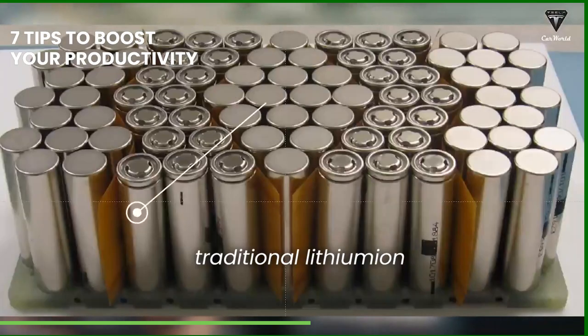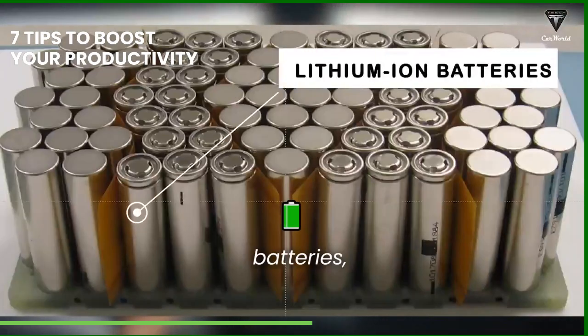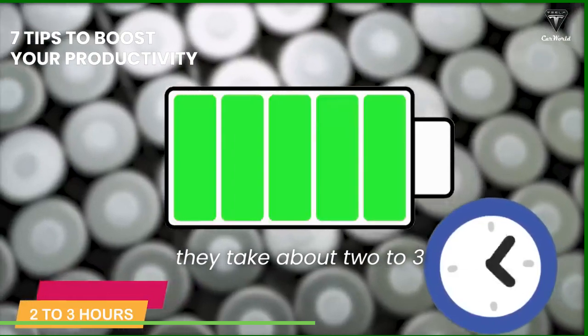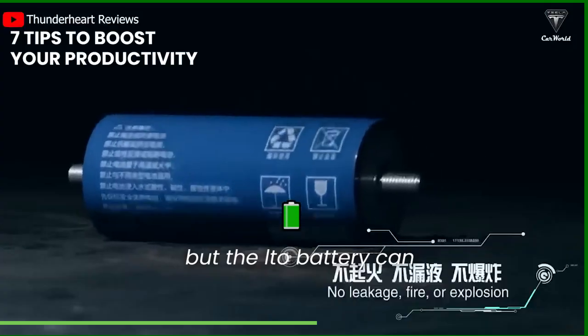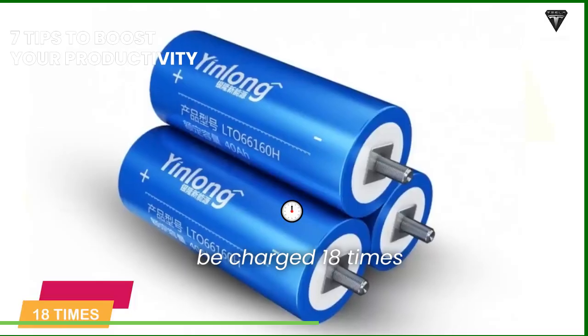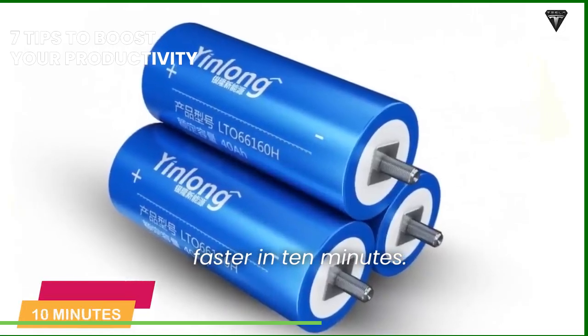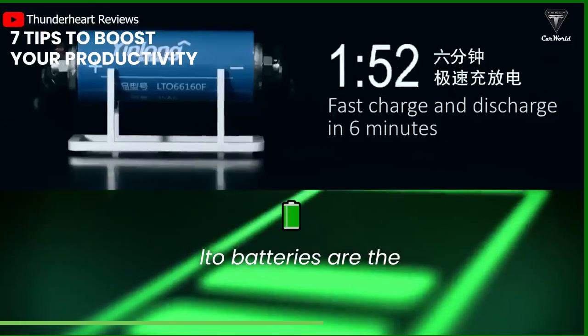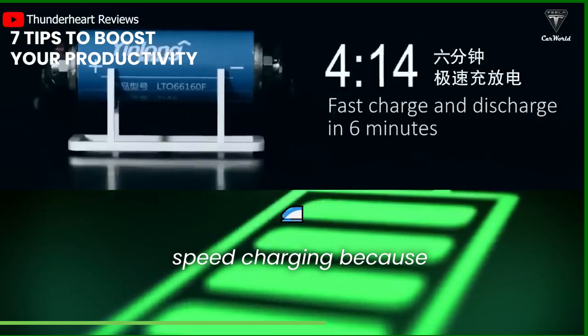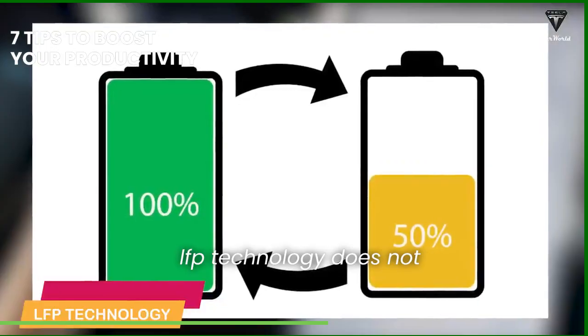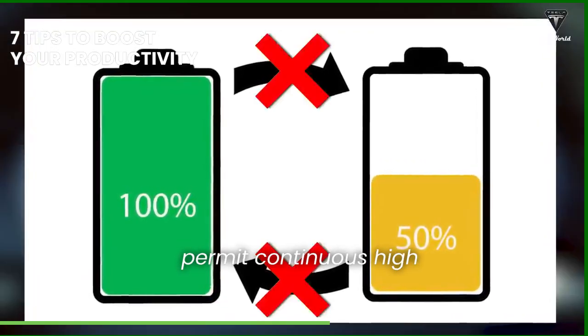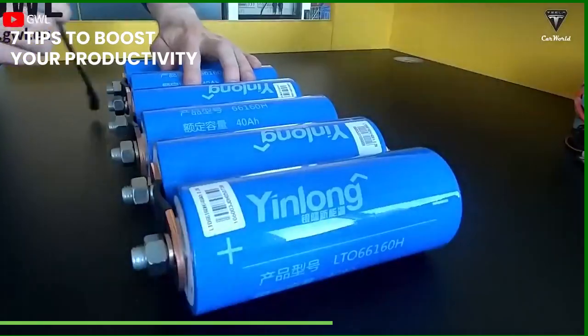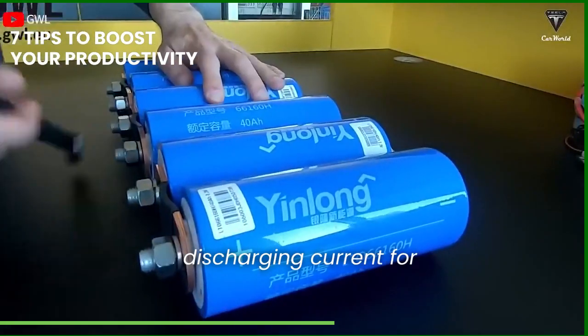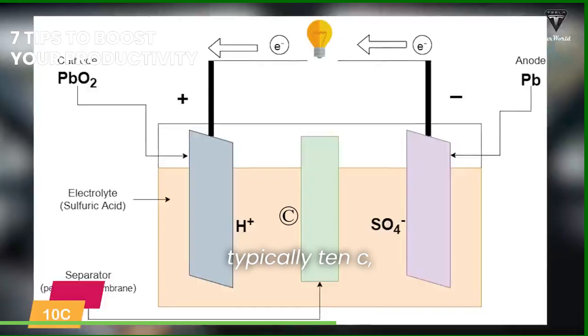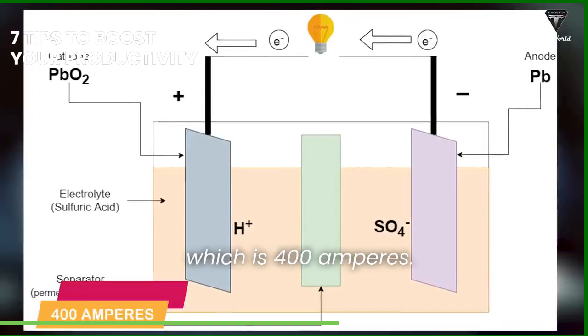When compared to traditional lithium-ion batteries, they take about 2 to 3 hours. But the LTO battery can be charged 18 times faster, in 10 minutes. LTO batteries are the sole option for high-speed charging because LFP technology does not permit continuous high-speed charging and discharging. The maximum charging and discharging current for this battery is typically 10C, which is 400 amperes.